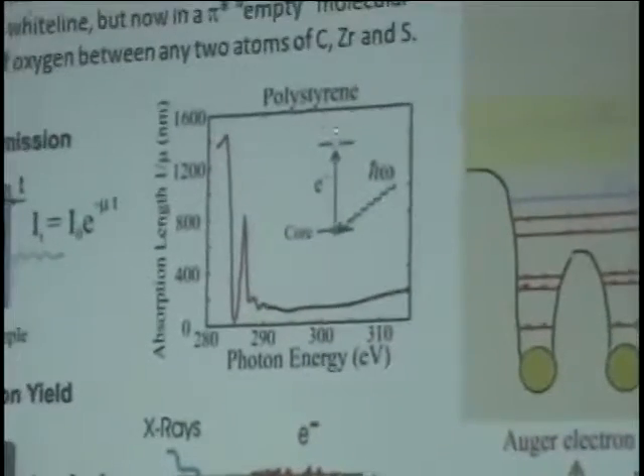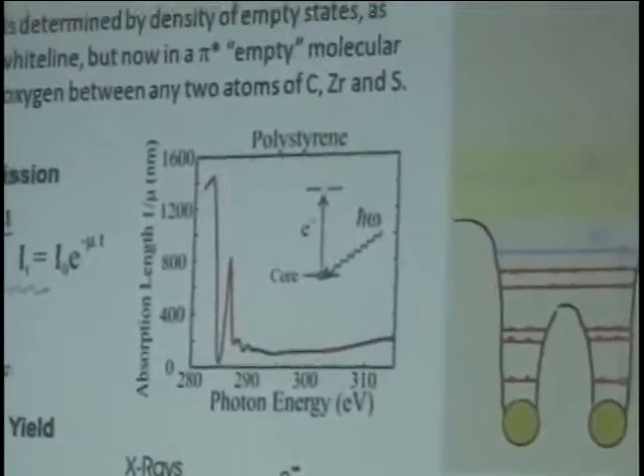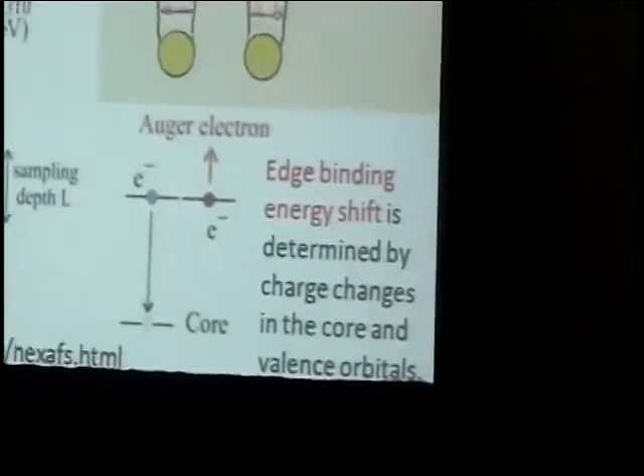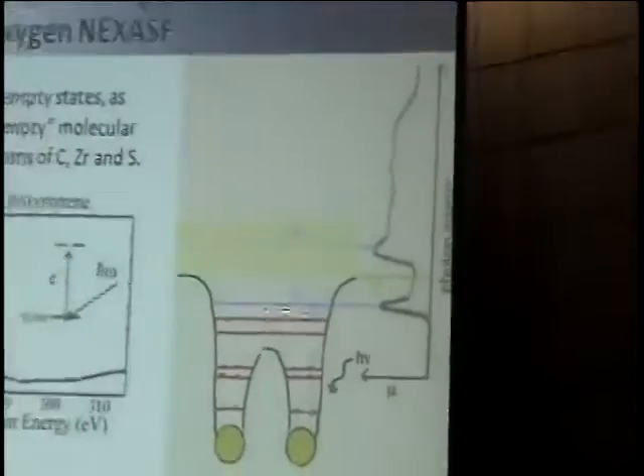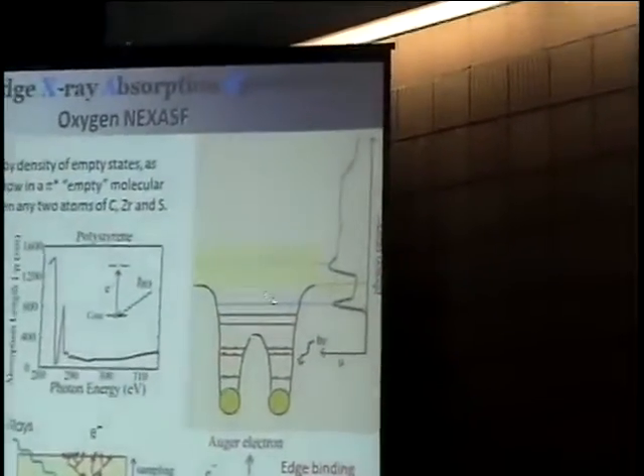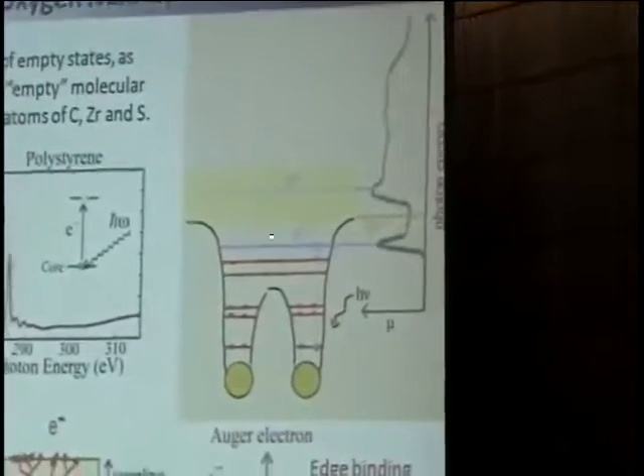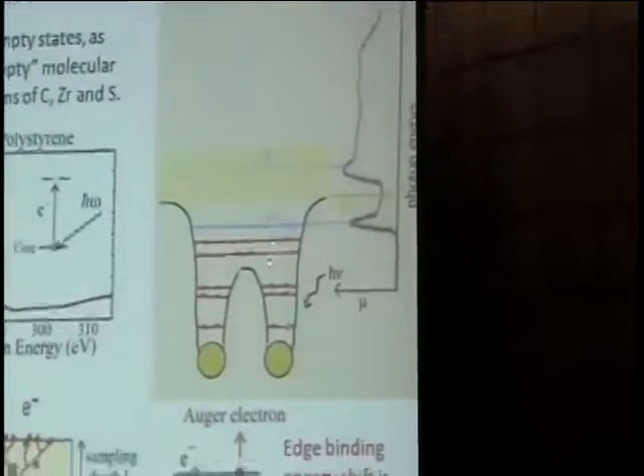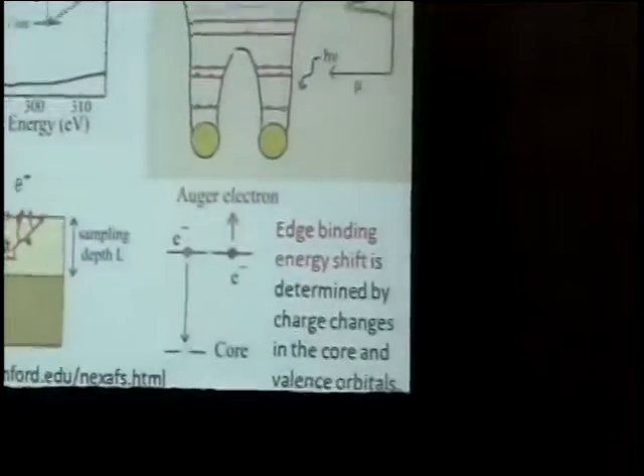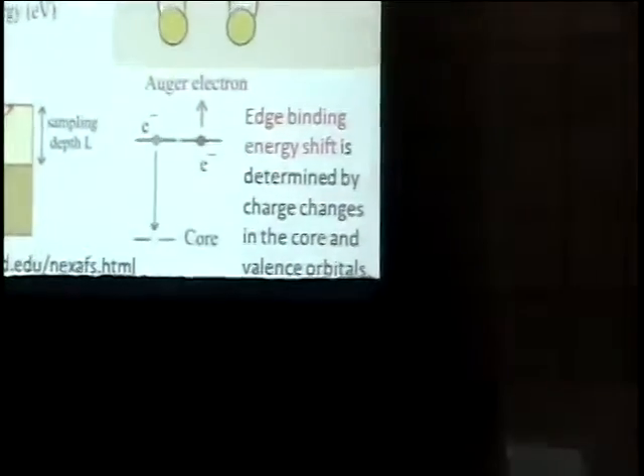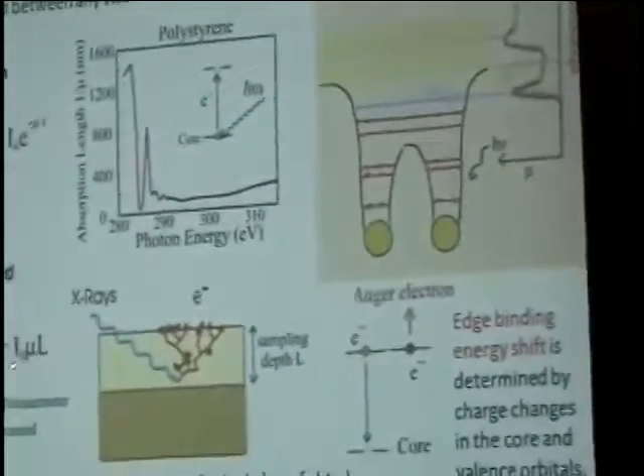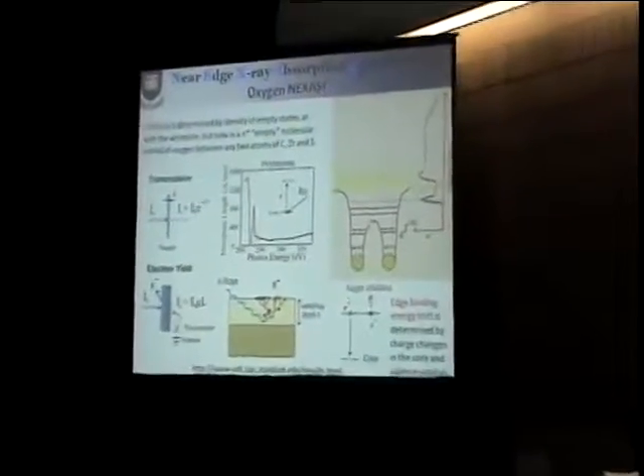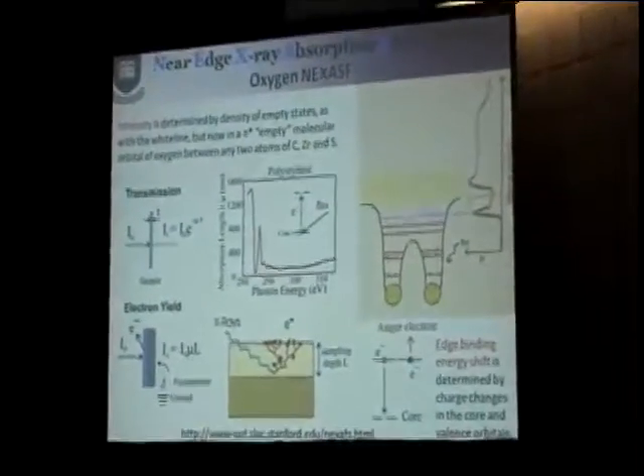And once excited, we have this electron excited into an empty orbital, and the orbitals I'm going to be using for carbon-carbon, carbon-oxygen, all of the cases I'm interested in here, will be an empty pi star between oxygen and some other atom. Once excited, it can decay either by fluorescence or by Auger process, but light elements almost exclusively de-excite by Auger process. And we're going to detect the electron. That makes it quite surface sensitive, within 2 or 3 nanometers of the surface.